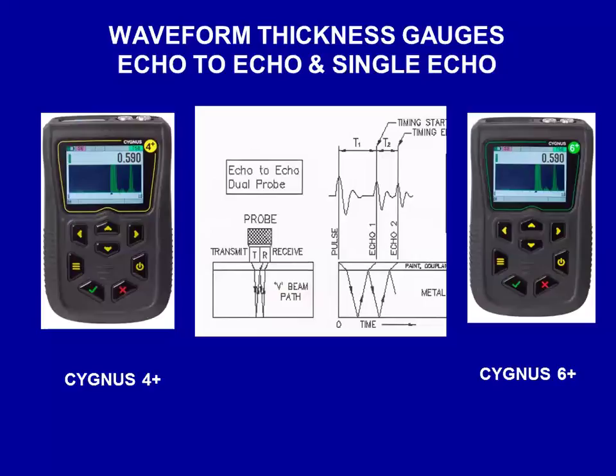Why do we do it? Because in that scenario where you can't get a measurement, I'll give you an example: divers. We have underwater equipment for divers. We have equipment for ROVs. But if the diver's doing a piling, and the piling is all heavily corroded, and he's using multiple echo, when he gets into that heavy corrosion, we never said no surface preparation. Our guys, the most important tool they ever carried with them was a chipping hammer. And if the steel is real rough and nasty, you take a hammer out and whale away at it. You've got to smooth it up.